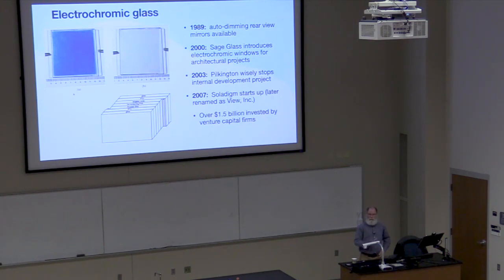But within a year and a half, we stopped the project. We just could not do it. We could make beautiful little laminates like this that would turn blue. But when we went to 12-inch squares, they did not look so good because it's such a sensitive material. I can remember one time we powered up our laminate and there was a beautiful fingerprint right there. You didn't see it there, but when you do it there, a little bit of sodium in the oil in your finger changed the color of that. So we stopped the project.